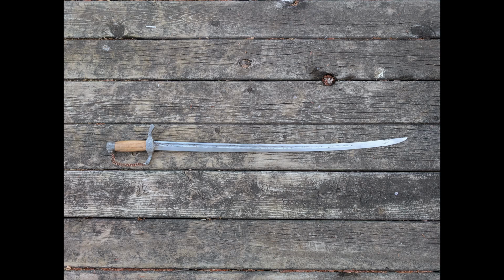mechanism results in much less residual stress than a traditional quench and temper. So as a result, there was essentially no risk of the blades warping during heat treatment. This alloy is also very tough, so the sword should be able to withstand abuse without fracturing. However, the trade-off is that this alloy does not get quite as hard as more traditional quenched and tempered carbon steel, but it still does achieve a reasonably high hardness that is in line with historical examples.